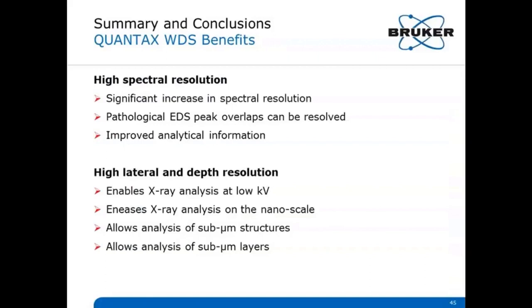WDS is perfectly complementing EDS, since WDS shows 10 to 20 times higher resolution than EDS. Thus, WDS can resolve pathological EDS peak overlaps. By using WDS, we gain more information about the sample qualitatively and quantitatively. The QUANTAX WDS is especially good for low X-ray energies. It is sensitive and shows high resolution capabilities for low energies.